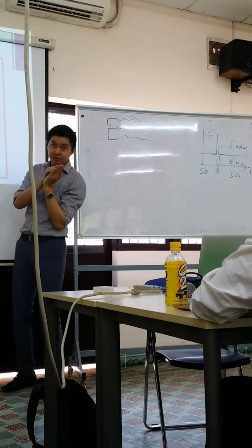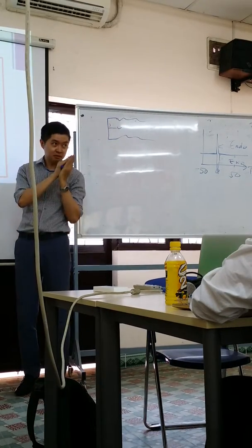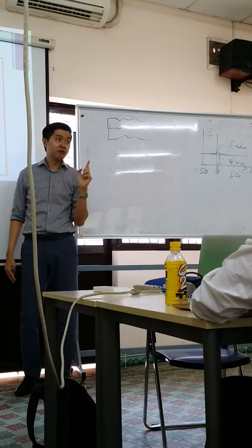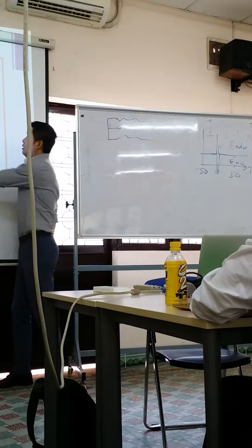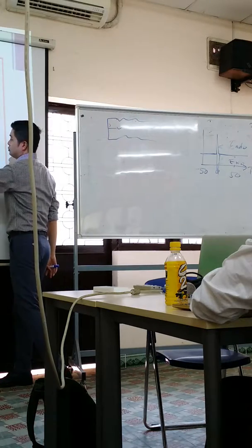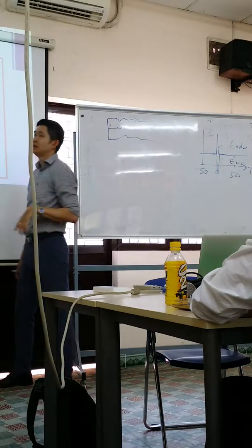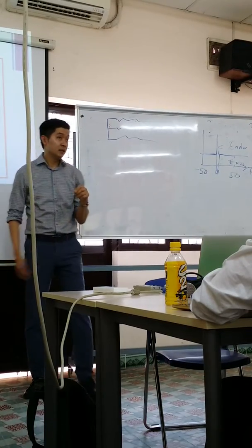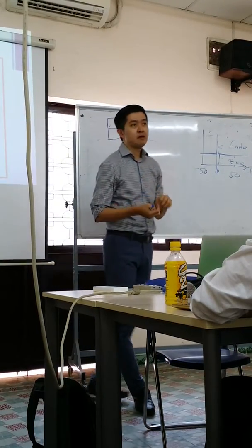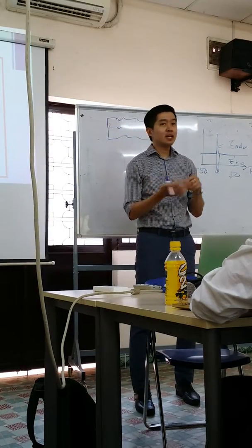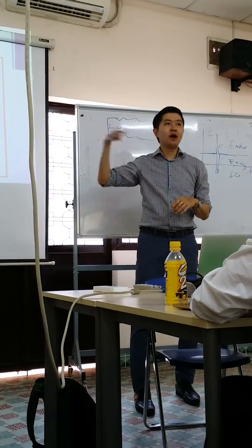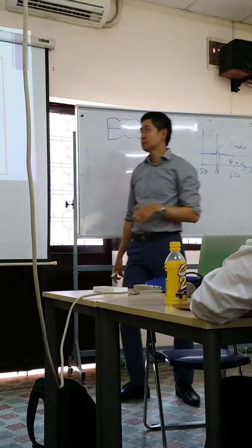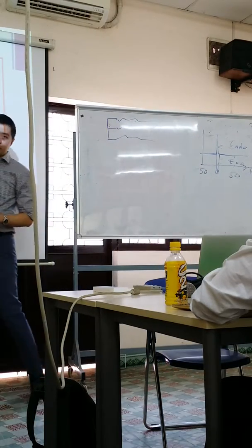It's still a tilted structure, which means they are not alpha, they are beta. But you have 1, 2, 3x. Then you call beta 3. So sometimes in literature or in textbook, they name it beta 1, beta 2, beta 3, and so on. So you must be able to explain these are the structure.